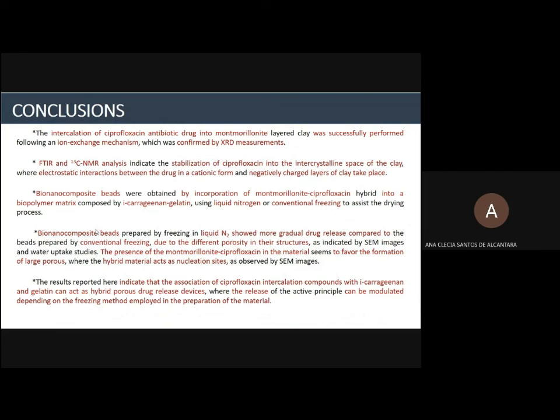The bionanocomposite beads prepared by freezing in liquid nitrogen show more gradual drug release compared to the beads prepared by conventional freezing, due to different porosity in these structures, as indicated by SEM images and water uptake studies. The presence of the montmorillonite-ciprofloxacin in the material seems to favor the formation of larger pores, where the hybrid material acts as nucleation sites, as observed by SEM images. The results reported here indicate that the association of ciprofloxacin intercalation compounds with iota-carrageenan and gelatin can act as a hybrid porous drug release device, where the release of the active principle can be modulated depending on the freezing method employed in the preparation of the material.